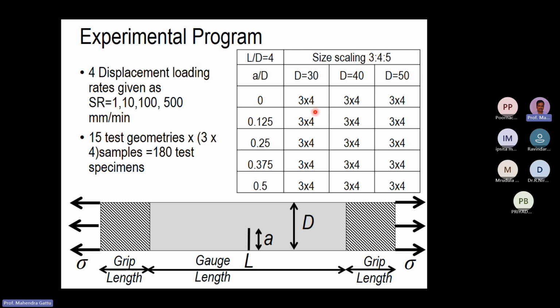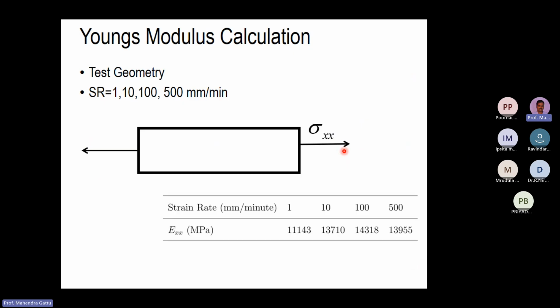And we cast around 3 specimens for each geometry, and for each geometry we did 4 loading rate tests. So in total we tested 180 test specimens, and that was for 0, which means there is no notch, and a by D of 1 by 8, 0.25 which is 1 by 4, 0.375 which is 3 by 8, and 4 by 8, which is 1 by 2. So all of this we tested.